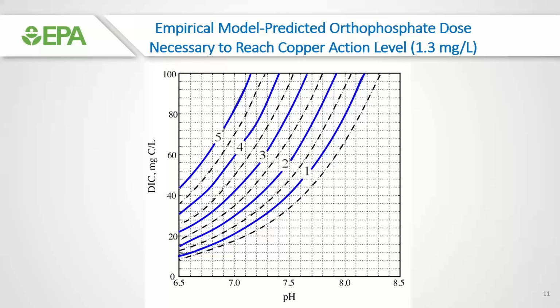Putting it all together, when it comes to orthophosphate, through a series of bench scale studies and precipitation experiments, we were actually able to put together an empirical model that, as I said before, fits pretty nicely with what really happens, because it is fairly predictable. We put this together as a guide in one of our Journal of AWWA, now Water Science, journal articles, showing the effect of orthophosphate dose at different DICs and different pHs to get us theoretically to the action level of 1.3 based on the worst case newer copper plumbing situation. So you can get a sense for how much orthophosphate you might have to add for your particular chemistry.